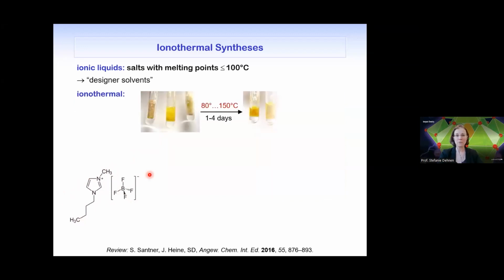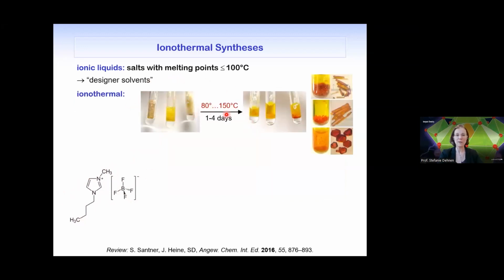And then you put them into ampules, heat them for some days, and this is what is summarized as ionothermal reactions. And if you're lucky, you get nice single crystals out of these reactions. So what you're doing is some kind of a solid state synthesis near room temperature. At least from the viewpoint of a solid state chemist, this is near room temperature.